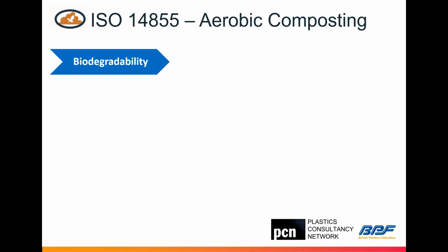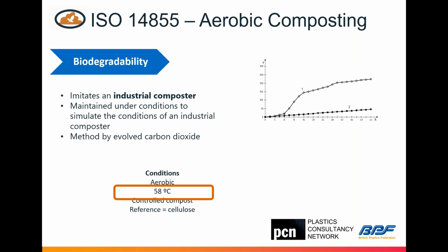So the ISO 14855, as I said, the main testing for biodegradability, imitates an industrial composter. It is maintained under conditions to simulate an industrial composter, and it works at 58 degrees. You use cellulose as a reference and blank compost as a control. As you can see on the graph, curve number one is the cellulose and number two is the blank. The difference between the CO2 production of the blank and the cellulose gives the ultimate biodegradation you get. In order for the test to be valid, you should reach 70% biodegradation of the cellulose after, I think, 4 weeks or so.